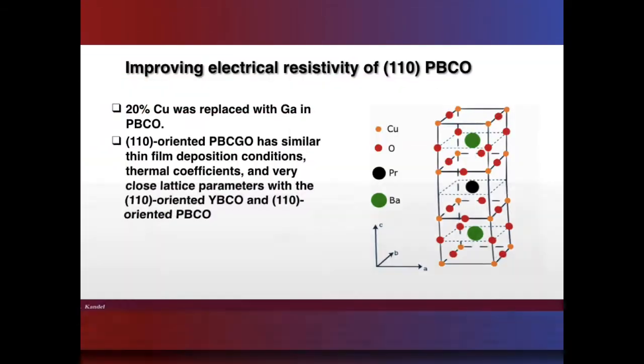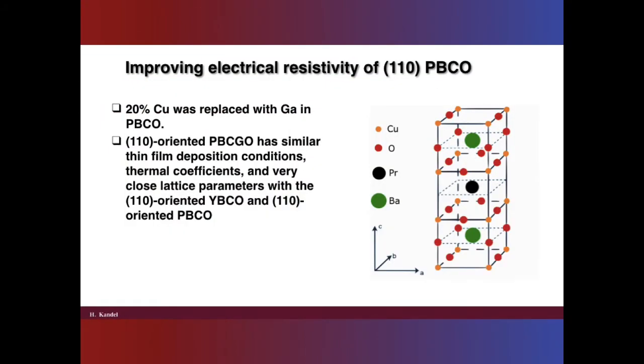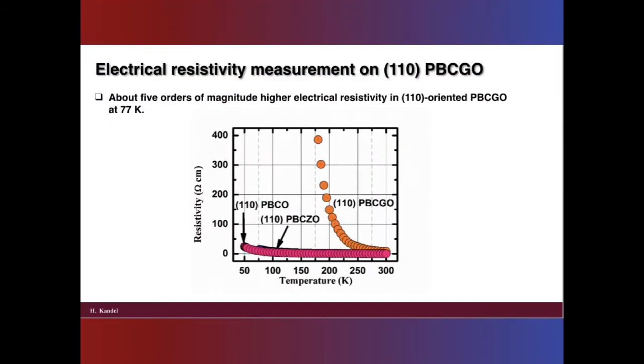Recently, though, we developed an excellent oxide insulator, 110-type gallium-doped PBCO, or PBCGO, by 20% gallium substitution. This insulator has very similar lattice structures, thermal expansion coefficients, and thin film growth conditions compared to our superconductor YBCO. Plus, its electrical resistivity is about 5 orders of magnitude higher than that of the PBCO thin film at 77 Kelvin.